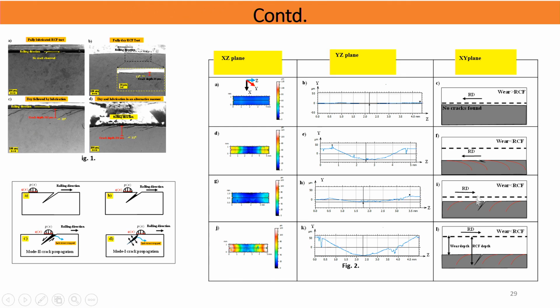And this is the kind of wear which is happening, as you can see. The rolling direction is like this. These are the cases of dry lubrication, and you can see a very high amount of wear. Now how did we get the wear? We measured the profile of the track, we just measured it.